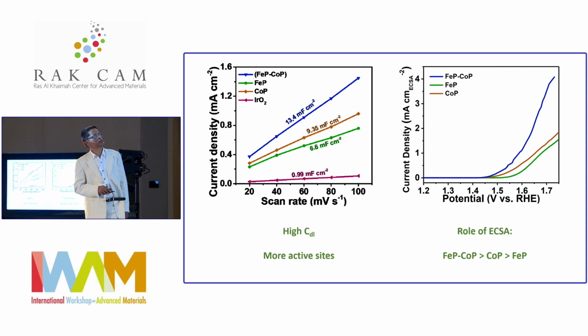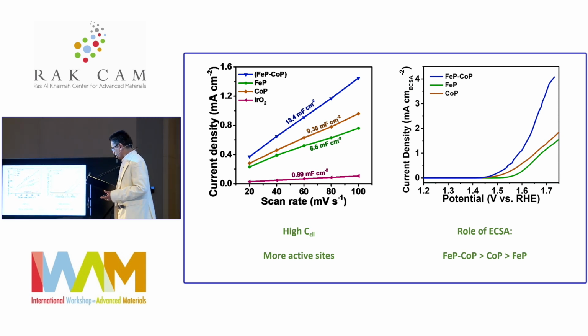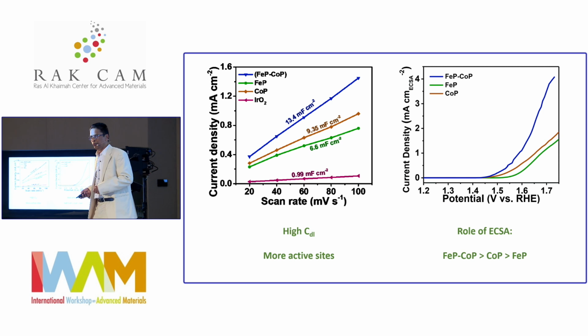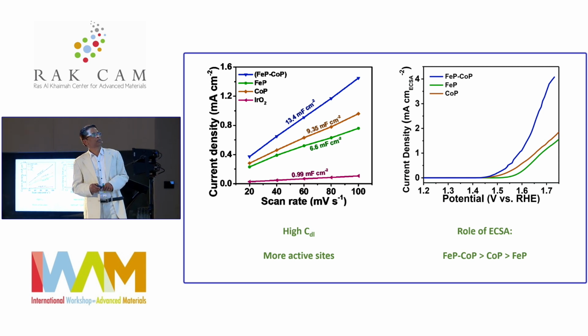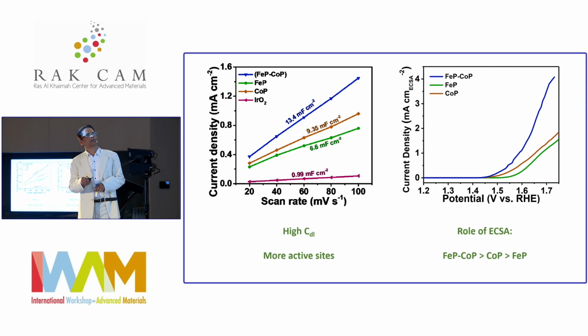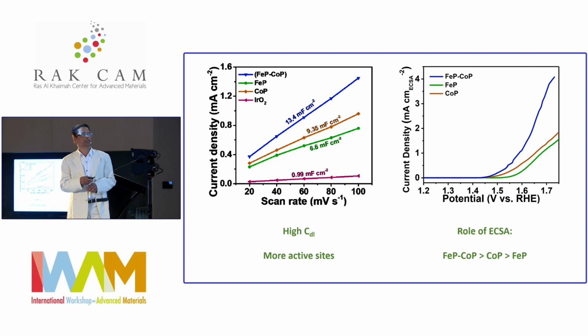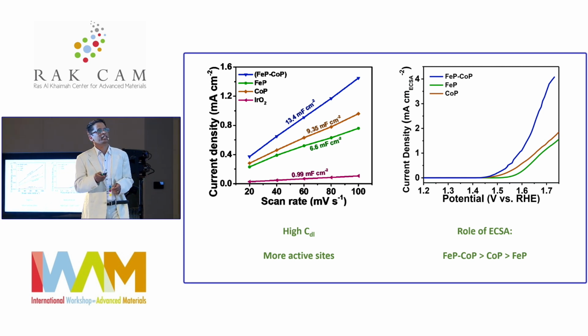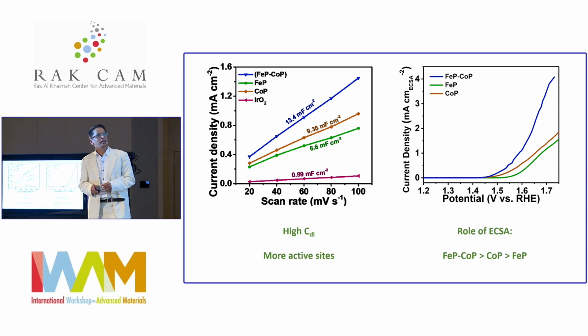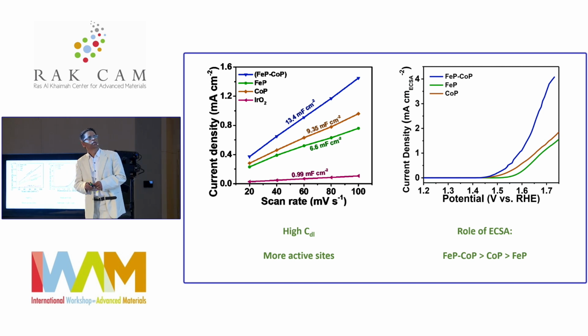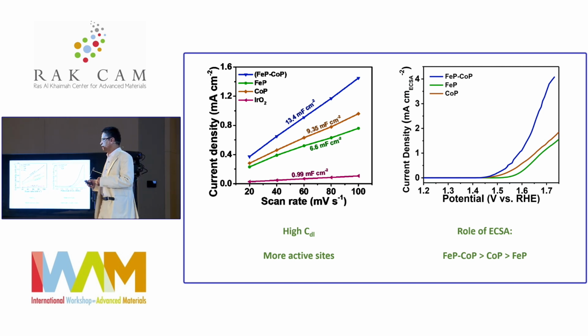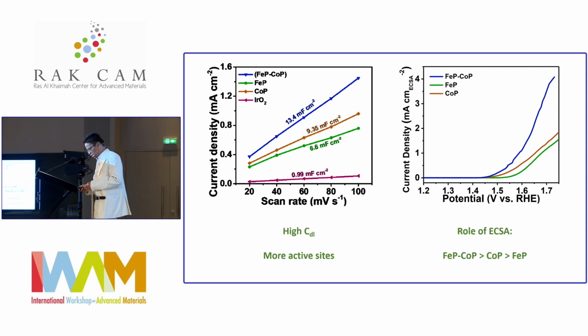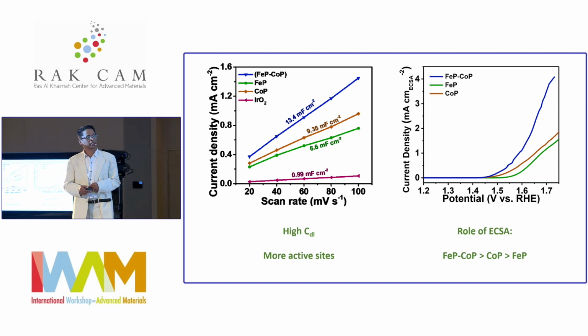That means one way to think of it is that mixing these two particles increases the number of active sites. But if it were just an increase in the number of active sites, then normalized to the current density it would not show any change. In this case, the normalized value is higher, which indicates that the intrinsic activity of this phosphide is increased by forming this heterostructure.